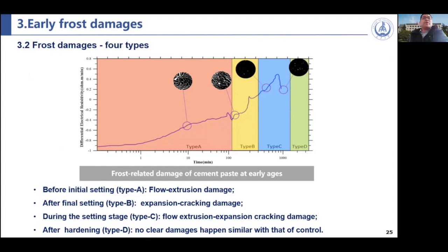After final setting, we define it as type B damage. In this part, the expansion and the cracking appear in the cement, and the cement pastes are broken by the expansion of the moisture. And also in this part, we call it type C damage. During the setting stage, the flow and expansion cracking damages happen together, and the strength will be reduced, and the performance is worse than the control.